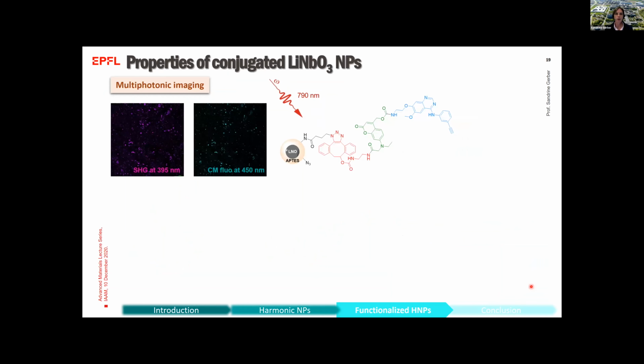And then we went for the imaging properties and drug release properties of the nanoparticles. So first, by irradiation at 790 nanometer, what you can see is that you can retrieve the second harmonic signal of the nanoparticles as well as the fluorescent signal of coumarin, which is an additional proof that we have made the conjugation of the ligand at the surface of the nanoparticles.